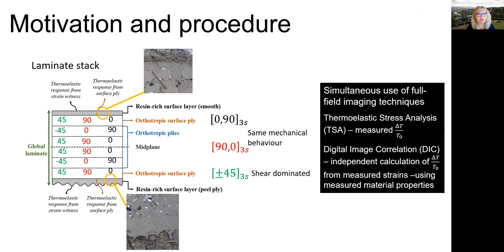We simultaneously used digital image correlation and thermoelastic stress analysis to give us a measured delta T upon T0. We were also able to derive an independent value of delta T upon T0 from the digital image correlation as we had measured the material properties.